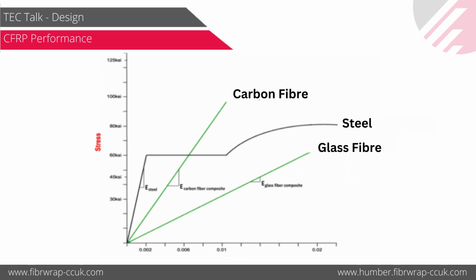So how we design the FRP is basically we take the modulus of material and the thickness of material from the data sheet, and then we derive the strain value depending on the guideline we are following, type of strengthening we are doing, and then multiply that modulus with the derived strain. That will give us a design stress for FRP for that particular requirement for that particular area. That stress should be used to calculate the area of FRP for a particular force. So that's a critical point. It is a very, very important point for designers, that FRP design will always be a strain limit design. It should never be designed based on the tensile stresses given on the data sheet.